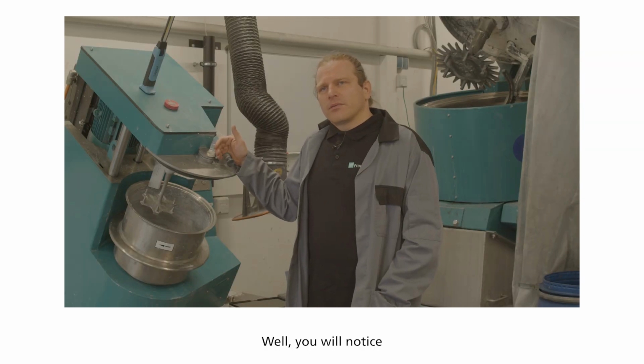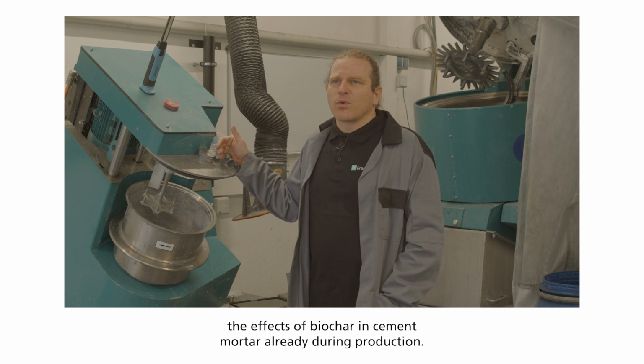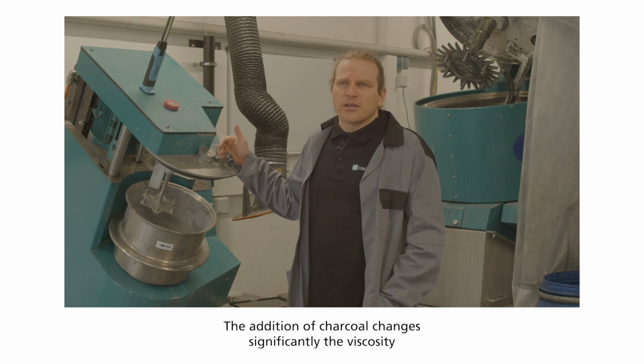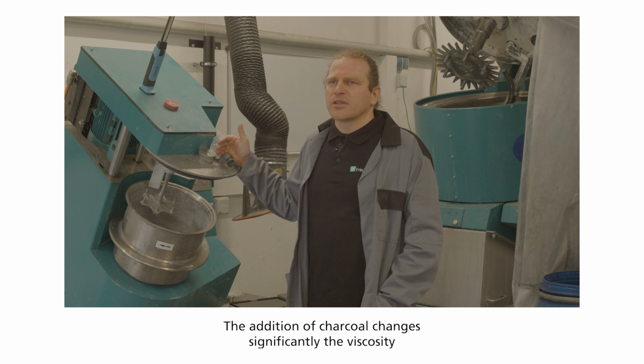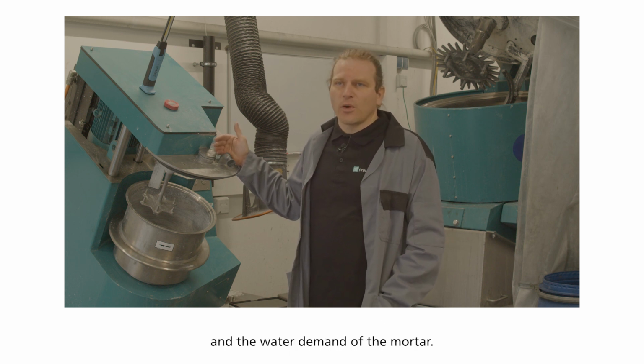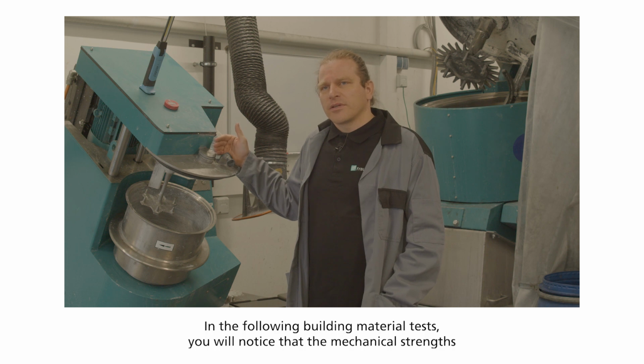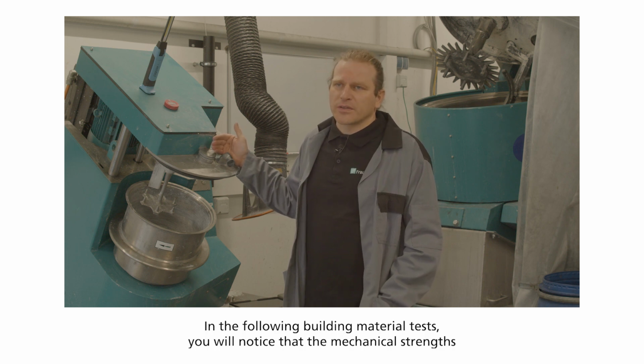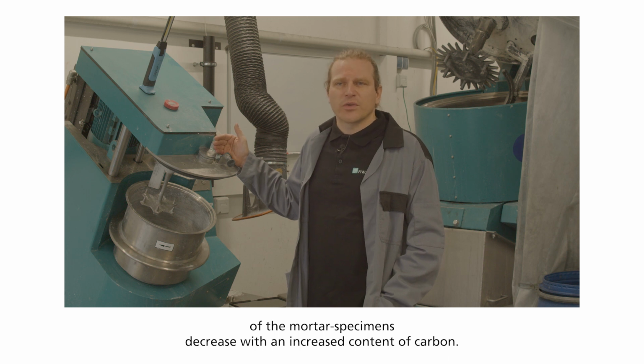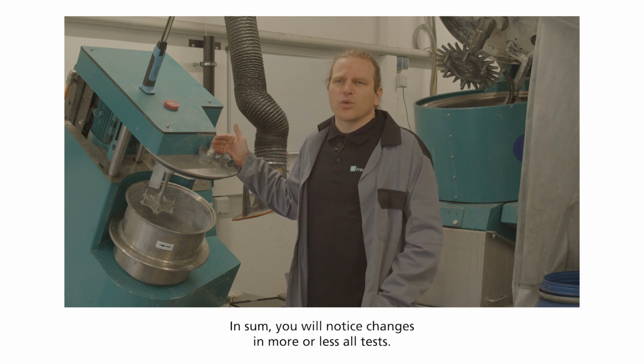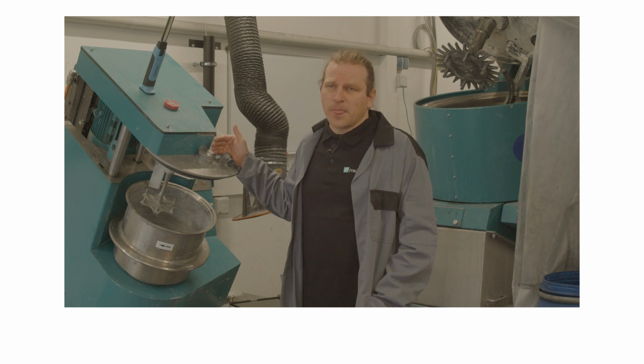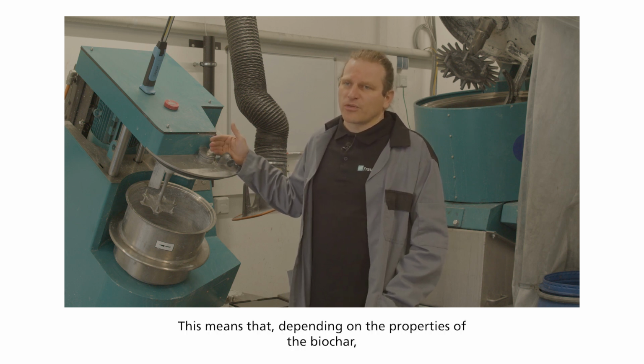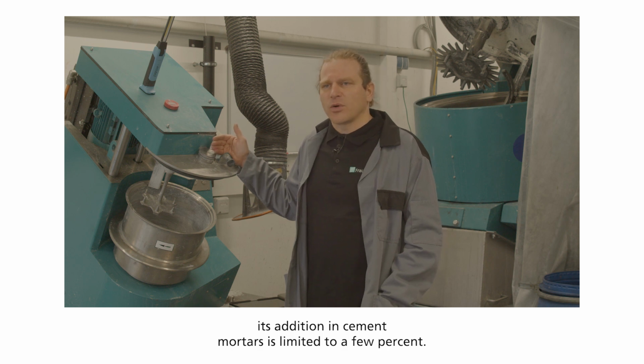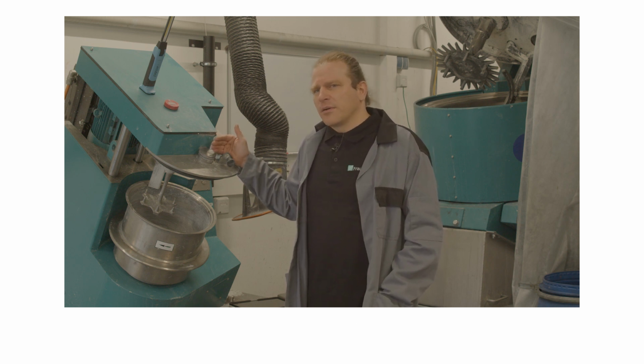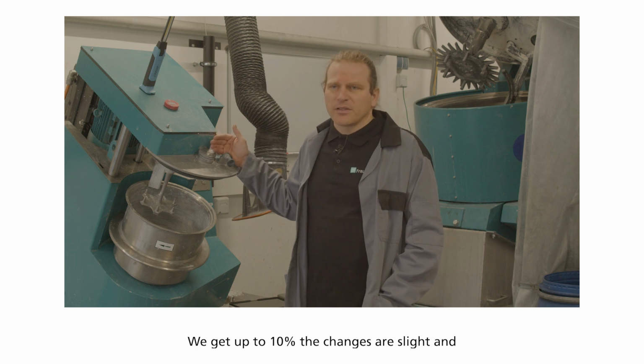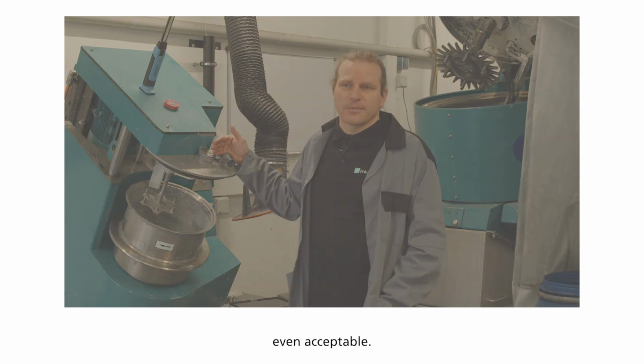Well, you will notice the effects of biochar in cement mortar already during production. The addition of charcoal significantly changes the viscosity and the water demand of the mortar. In the following building material tests, you will notice that the mechanical strength of the mortar specimen decreases with increased content of carbon. In sum, you will notice changes in more or less all tests. This means that depending on the properties of the biochar, its addition in cement mortar is limited to a few percent. We guess up to 10%, where the change is slight and even acceptable.